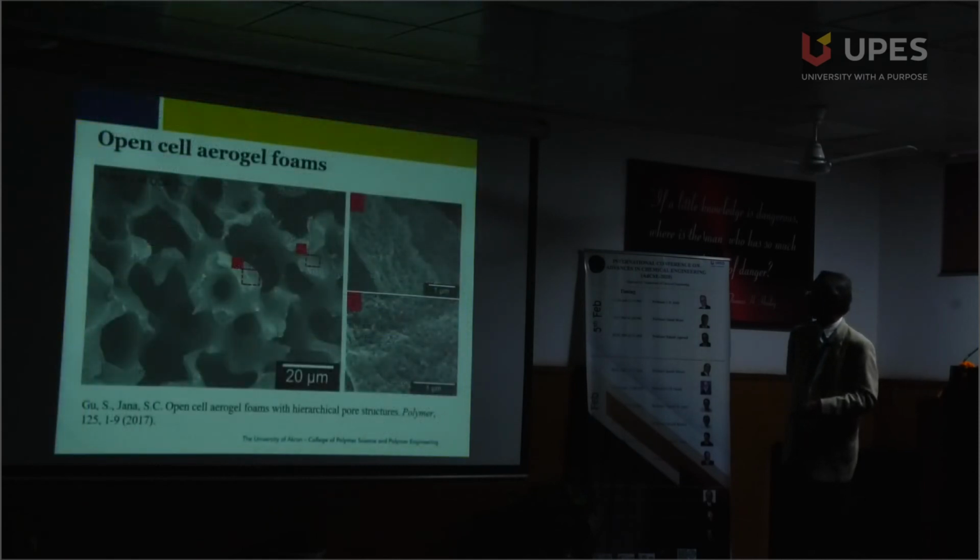So now we want to increase airflow. One way to do that is to create something called aerogel foam. So we had aerogel, now we create a foam-like structure through emulsion templating. These are some of the large pores through which air can flow, but there are these kinds of skin materials, which are aerogel materials through which air has to go, but now this convection distance is shorter. As a result, the permeability goes up even a factor of 10 higher than the aerogel.